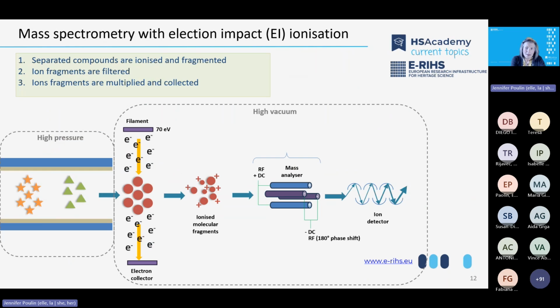When the separated sample reaches the mass spectrometer, it moves from a zone of high pressure to a zone of high vacuum. As each component exits the column, the molecules are immediately bombarded with an ionizing electron stream, and this bashes the molecules apart into smaller pieces, and each piece has a positive charge. In EI mass spectrometry, the electron stream is a constant 70 electron volts. Every time a molecule is subjected to this, it is going to break apart in the same manner, just like a fingerprint. These charged fragments get filtered in the mass analyzer, then they're amplified and detected in the ion detector according to their mass to charge ratio. And what we then see is a chromatogram and a fingerprint mass spectra for each peak.